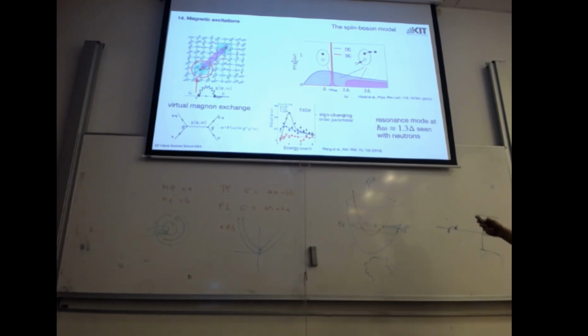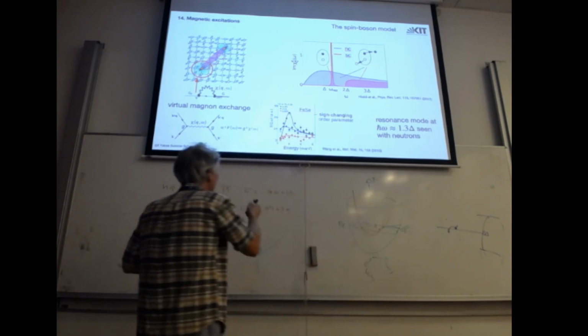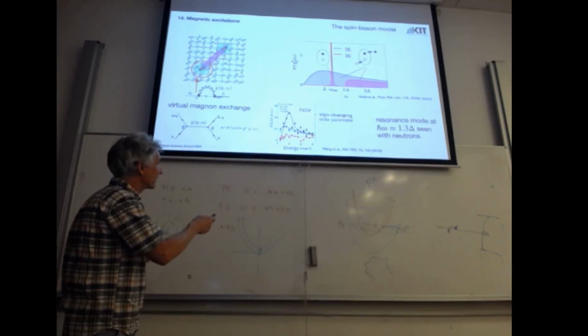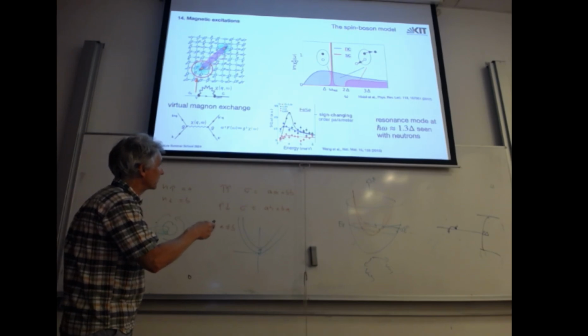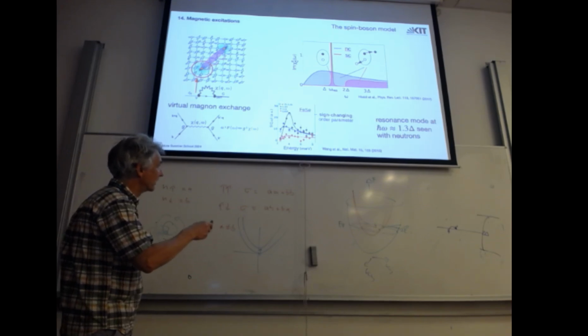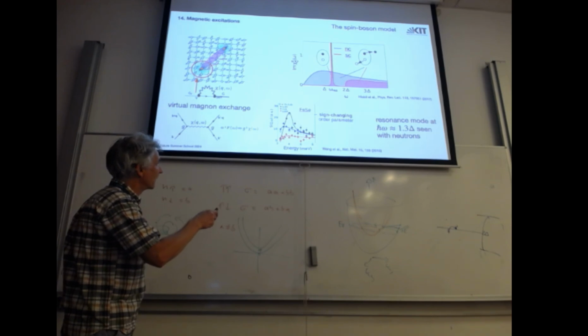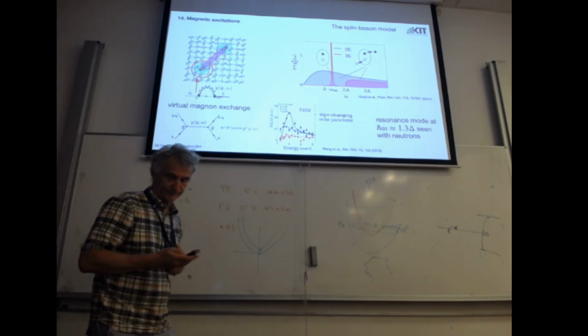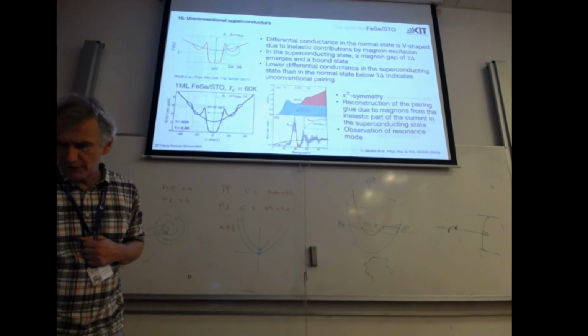And the interesting thing is there's a bound state in this gap, which you also can see in neutron scattering, and it's a long-lived state. Single particle states. So that is something that was also experimentally seen here. I said this is an unconventional superconductor. You see the magnon, the magnetic excitation spectrum, energy resolved. If you go below TC, then you get a black curve, there is this resonance appearing. How would that show up in STM?